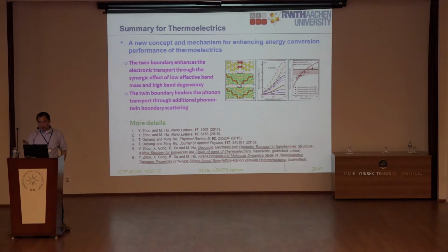So to summarize the thermoelectrics, I just want to say that we propose some new concepts and mechanisms for enhancing the energy conversion. For example, the twin boundary enhances the electronic transport through this synergy effect of low effective band mass and high band degeneracy. And the twin boundary, of course, scatters phonons, and then the thermal conductivity also goes down. The detailed study can be seen in our recent Nanoscale publication.